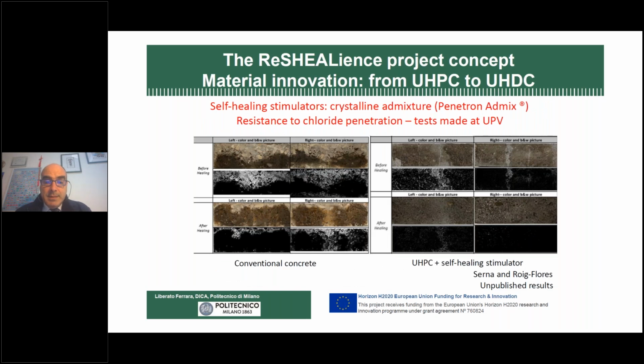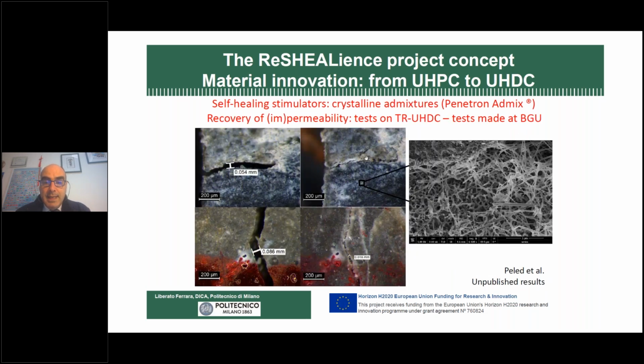Here are some examples. On the left, you have a conventional concrete, chloride penetration. On the right, you have our materials. This was developed at Universitat Politecnica de Valencia, and you can see with our materials, not only do you have a very narrow crack, with penetration limited at the very beginning of the cracked surface life, but with the healing, you almost reduce it to zero. You do not see any more chlorides in the material.